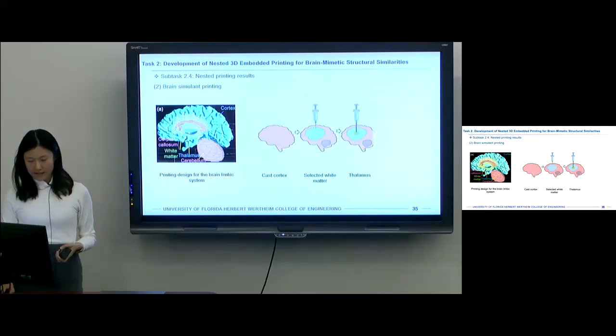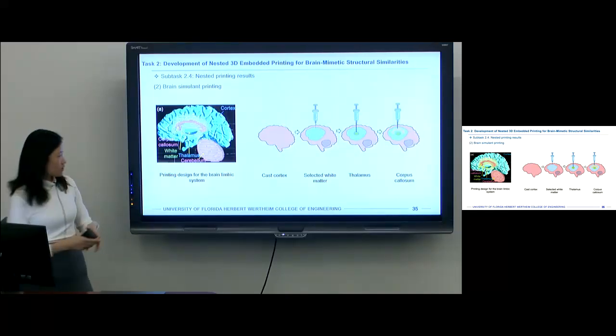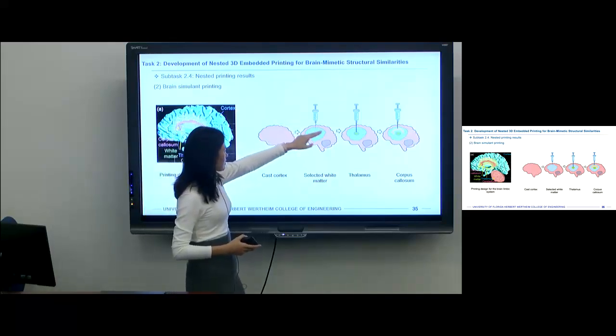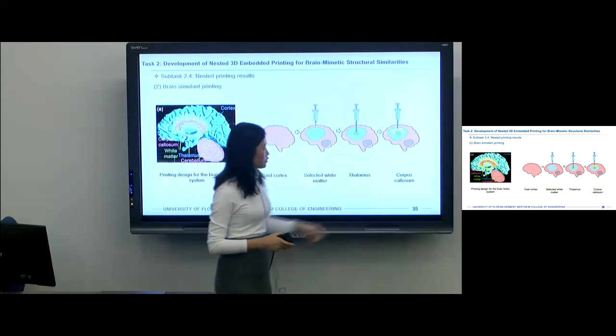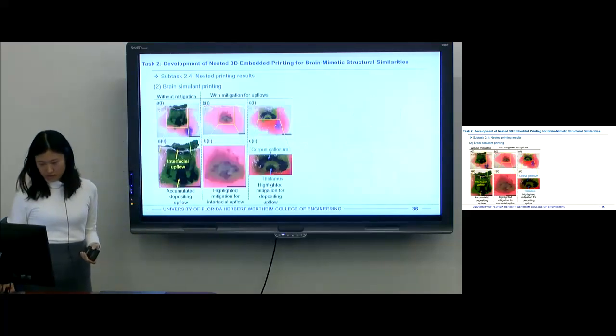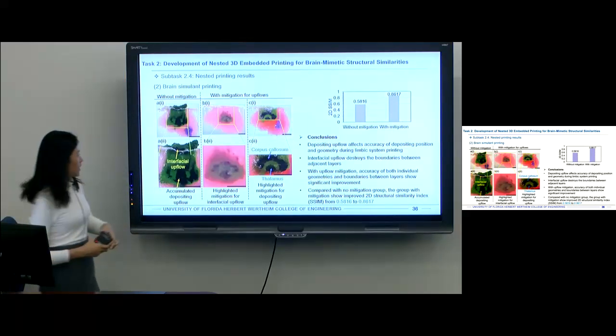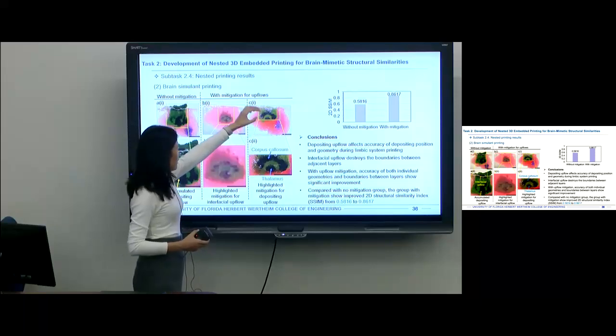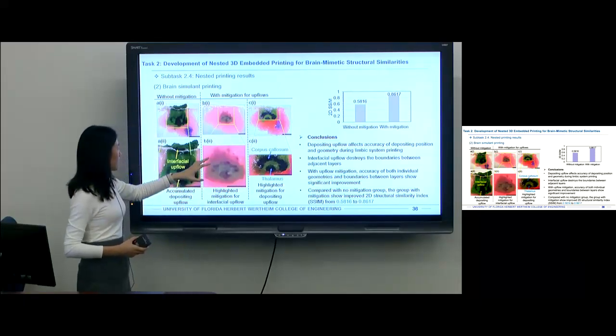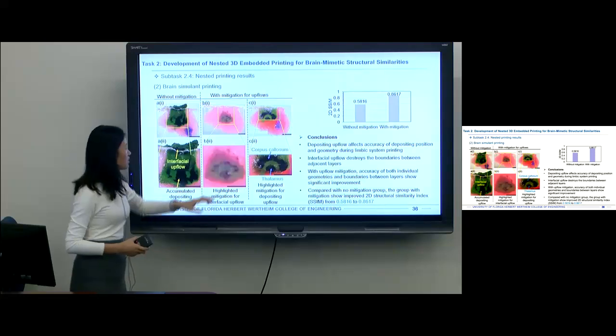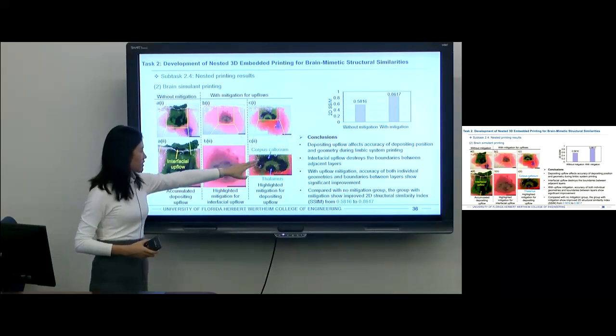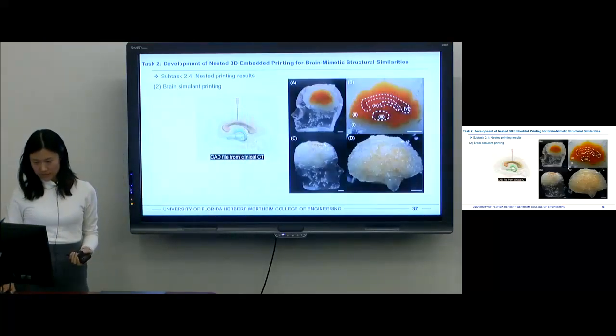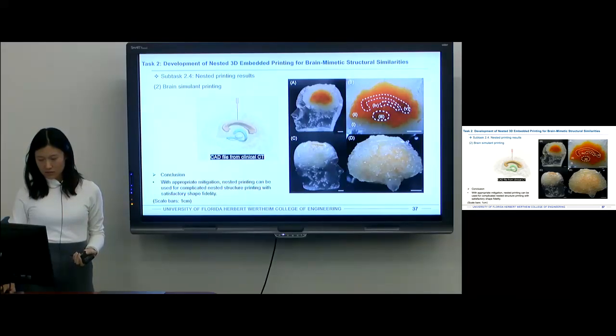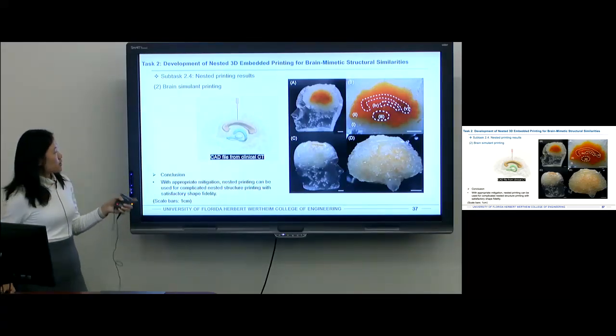And then we applied this method to our brain simulant printing. We have the first depositing structure, second depositing structure, and third depositing structure. And we have the printing result here. Without the mitigation, it can have huge upflow. And with mitigation, we have clear boundaries and well-defined regions. So this is our brain simulant printing result.